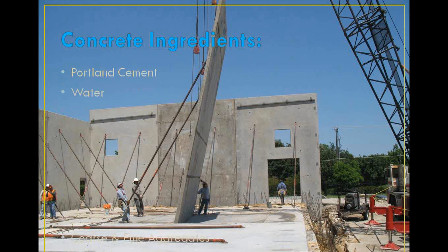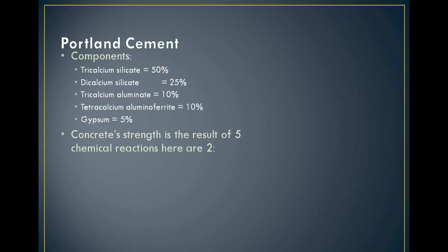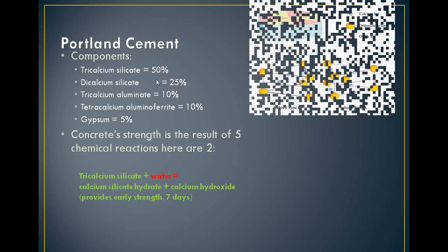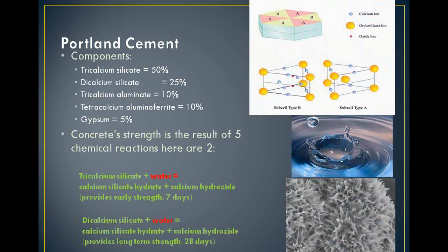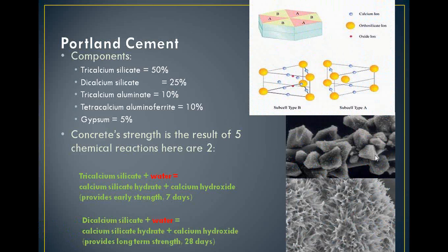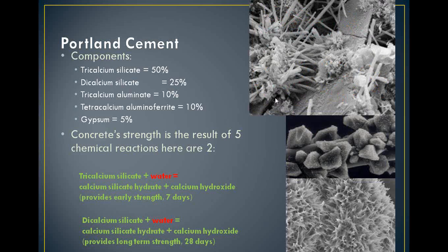Concrete is comprised of Portland cement, water, stone, sand, and admixtures. Not an inch of concrete gets poured in the civilized world without some sort of an admixture in it. If you were to take Portland cement out of these ingredients, what you would have is a pile of wet rocks and sand. So that's where we need to look carefully, because that's where the magic happens. 75% of Portland cement is comprised of tri- and dicalcium silicate. And when these silicates react with water, they form calcium silicate hydrate and calcium hydroxide. This is what provides the early and long-term strength to concrete. The additional materials form the completed matrix of the concrete, and that's what you have.